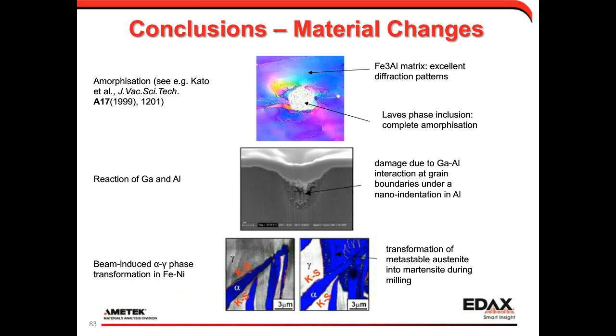With ion beams, you can also get some funny effects. In some cases, you can cause a crystal structure to become amorphous. In other cases, you can get reactions of the ions with the material. An example here is gallium and aluminum causing issues. And in other cases, you can get beam-induced phase transformations, where the energy of the ion beam can be a driving force for a transformation of material.